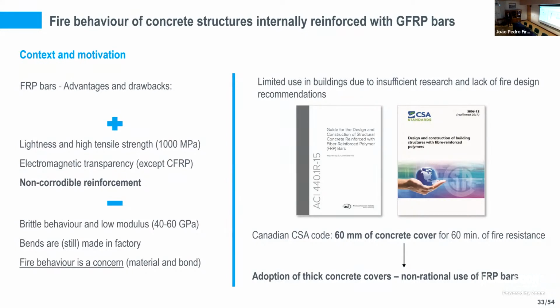One of these recommendations that I would like to mention is the one provided by the Canadian Code, which said that to have a concrete member reinforced with GFRP bars with 60 minutes of fire resistance, we should adopt a minimum concrete cover of 60 millimeters. Well, for FRP bars, whose main advantage is not being susceptible to corrosion, it's a non-rational use of these bars, because if you are adopting a very high concrete cover to solve the fire issue, we are not taking advantage of the high durability of this material.